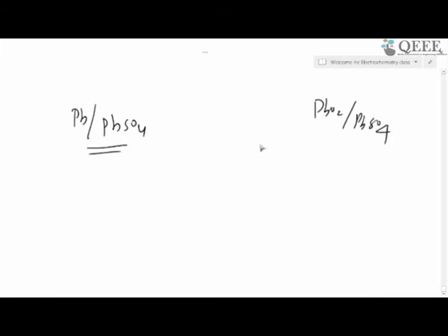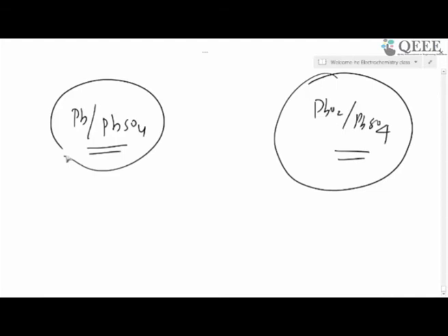Between these two redox couples, if one of them is very slow electrochemically, that means less reversible compared to the other one, generally we design a cell where the irreversible material is kept a little more, because of its poor reversibility, so that the battery can maintain the capacity for a sufficient number of cycles.